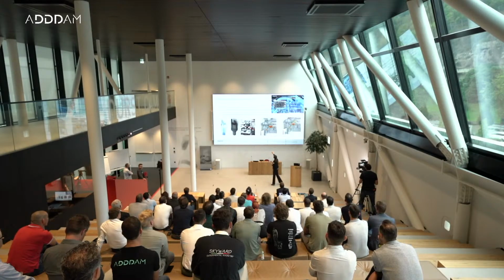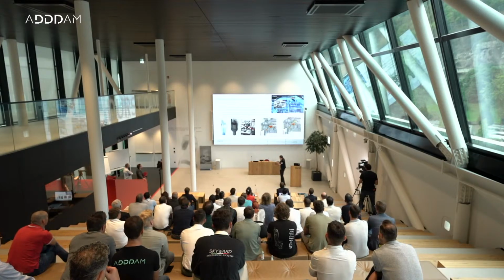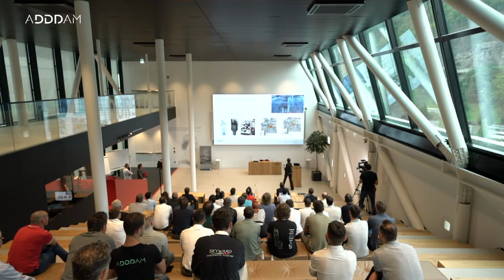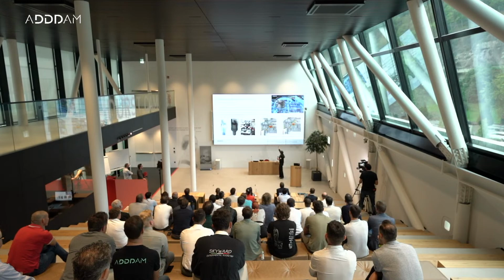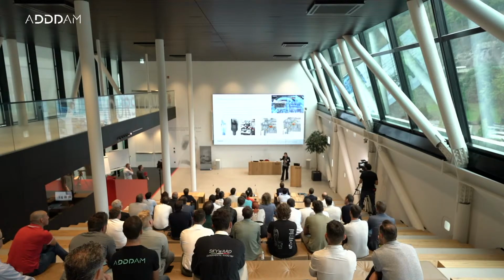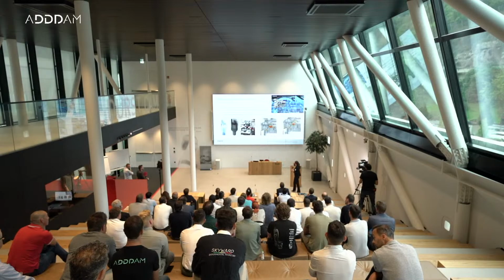And here in the simulation, we have this reddish area. That means I have a macroscopic shrinkage later. I have a hole in the material, which I don't want to have. And you see here, where this greenish area is, we optimized actually this die with an insert with near net shape cooling, and we could reduce this area, improve the material. So this is also how we use AM since 2018, since several years in production.